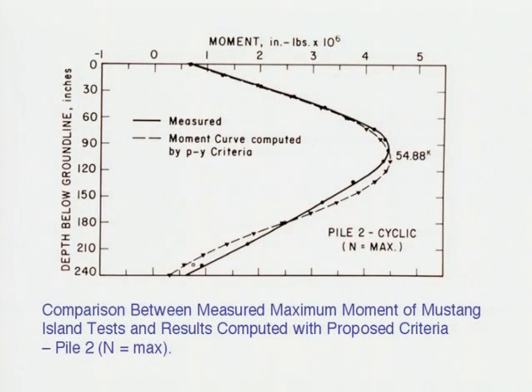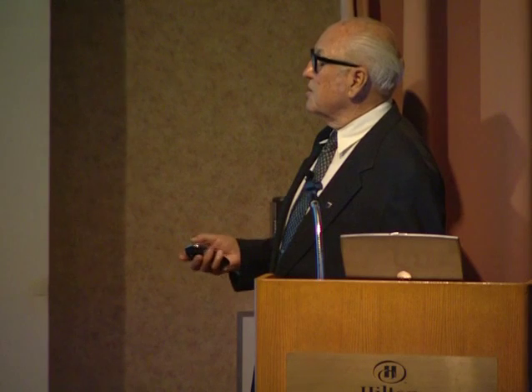Now here's the result for cyclic loading, again up near the maximum bending moment, somewhat less load, about 55 kips now instead of 60. And again, with the PY curves for cyclic loading, we're getting a reasonable agreement, or good agreement, between the computed values and the ones that were measured by the strain gauges. So we have a set of PY curves that work very well, and as I mentioned before, we'll use those PY curves and glean all the data we can from the literature on uninstrumented tests. Very few instrumented tests have been run to give us some confidence that the PY curves are giving us reasonable values.